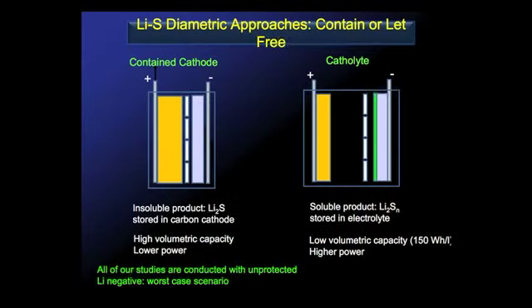These were commercialized by Scion Power, working together with PolyPlus. And these cells have some advantages. They have high power because they're effectively a liquid electrolyte system. The product is stored in the electrolyte, but they have rather poor volumetric capacity, typical values are 100 to 150 watt-hours per liter.